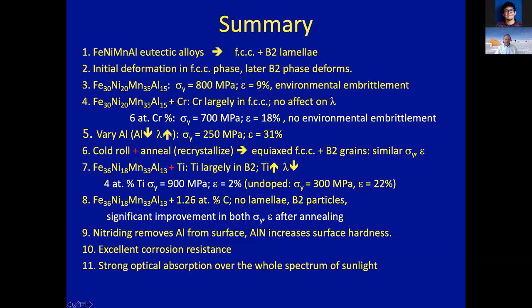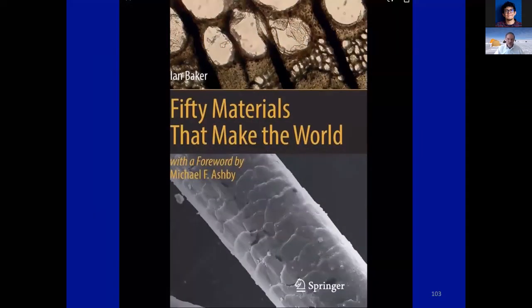We added carbon to the material, and carbon completely changes the microstructure, so we don't get lamellae. After annealing, we get B2 particles. And the carbon doped material has both good yield strength and good elongation to failure after annealing. We also looked at nitriding the material, and nitriding essentially removes all the aluminum from the surface and produces aluminum nitride, so it increases the surface hardness. So we've shown that we've got excellent corrosion resistance, better than stainless steel, and strong absorption over the whole spectrum. So with that, I'll finish and answer any questions that have come up.